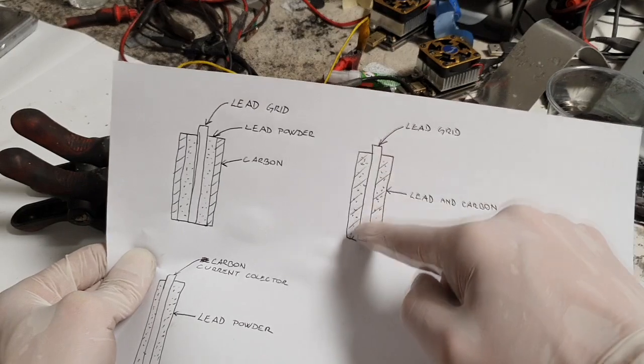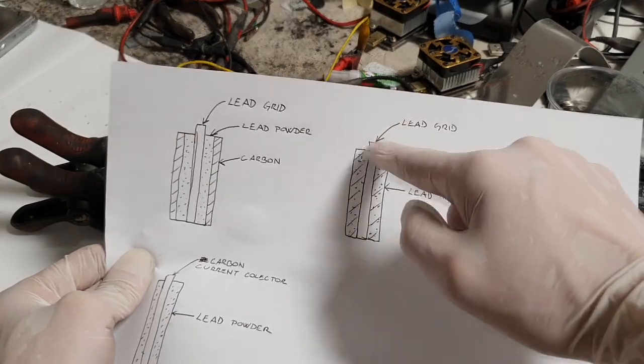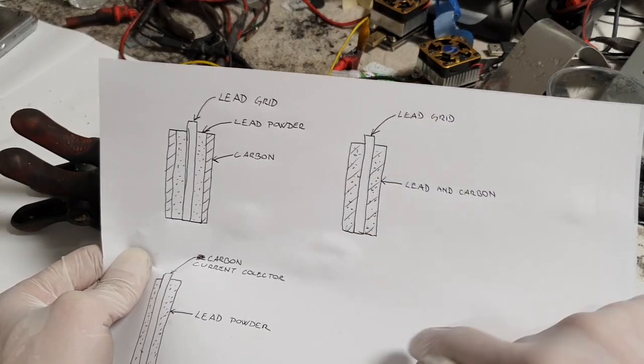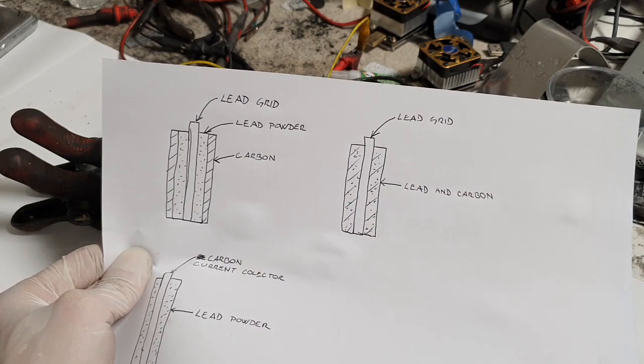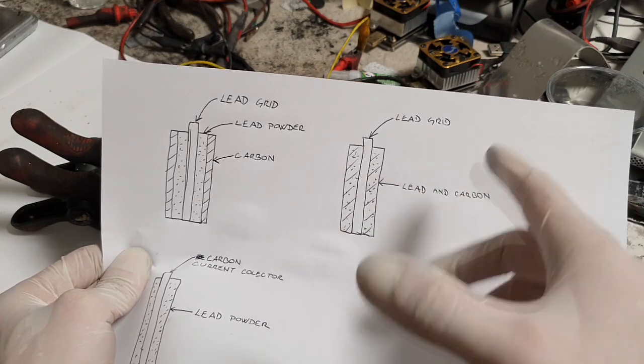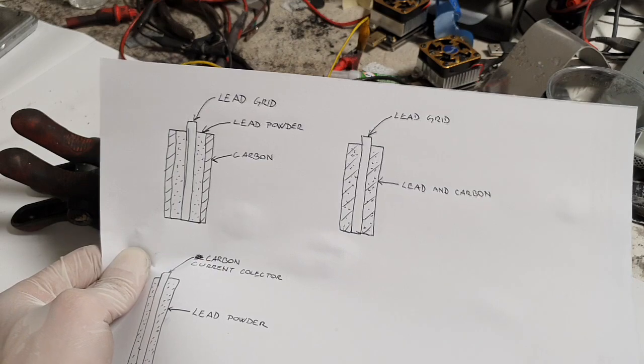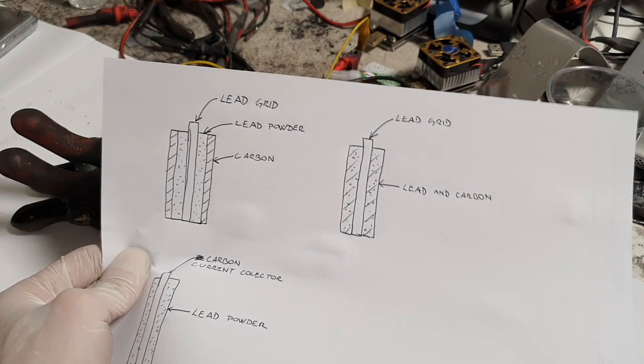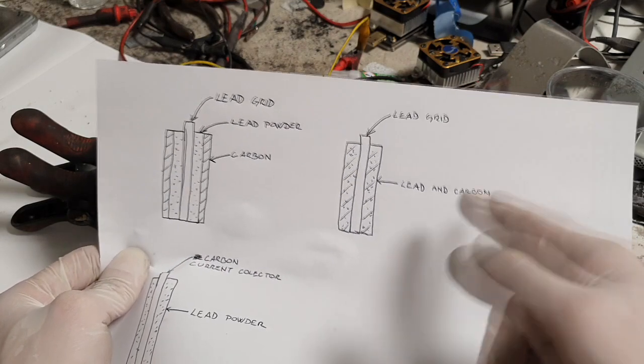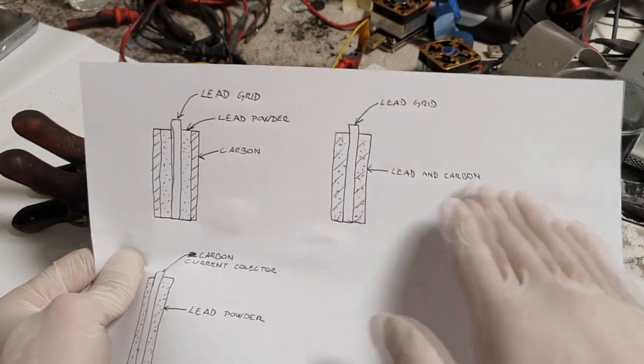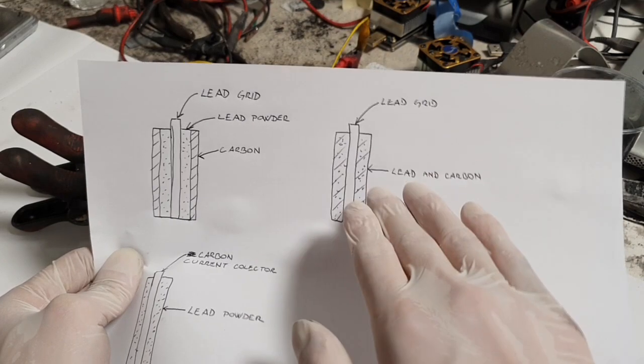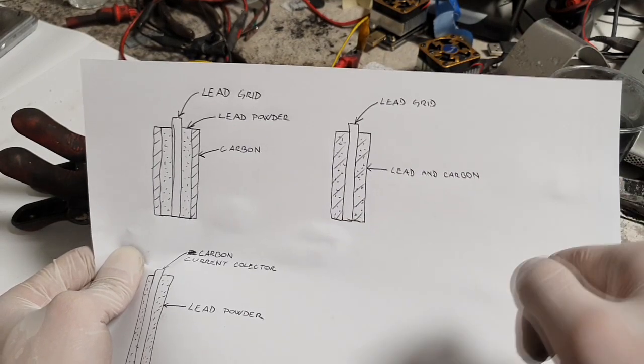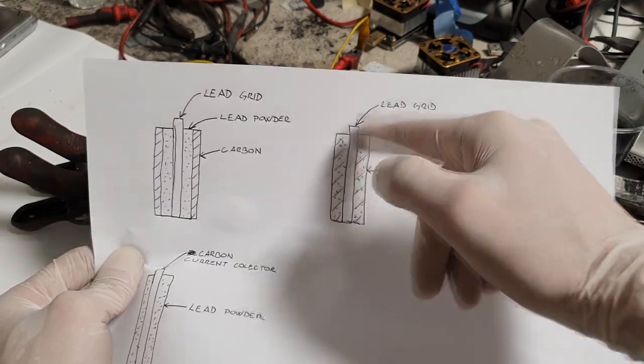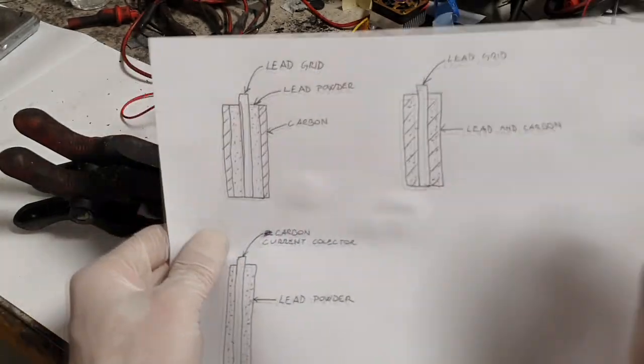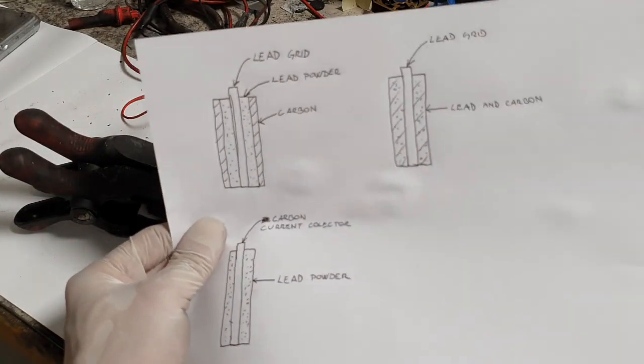The second design of this negative electrode is this. Again, we have the current collector, which is made from lead grid, and the active material on this one is a mix of lead powder and carbon, in our case activated carbon. So you mix activated carbon and lead powder together, add some binder and put it on this lead grid, and this design is also really, really good.